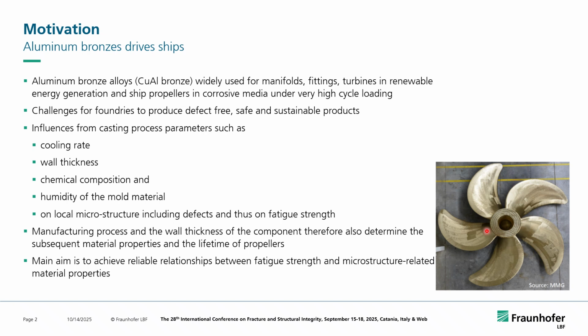The humidity of the mold material is a point that we want to consider and talk about, because the humidity and the production of the mold at the end consumes a lot of energy, and the drier the molding material is, the more energy we have to put into the manufacturing process beforehand to get it dry. And at the end, all those parameters will influence the local microstructure, including then defects, or hopefully not having defects, but at the end, the fatigue strength.